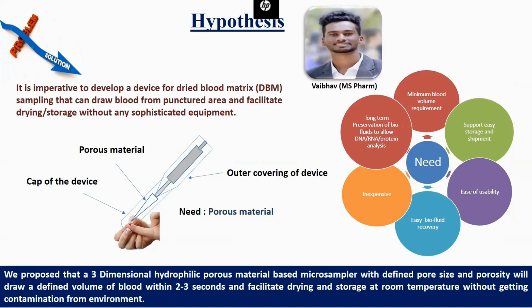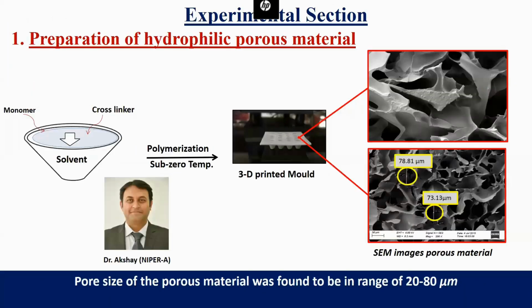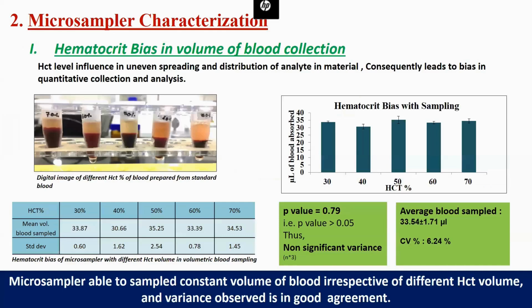So with the help of this MSc student who worked with me, we developed this device. How did we do it? We created a specialized hydrophilic polymer material with the aim of IP protection. I am not going to share the chemical name, but we had some hydrophilic polymer material that we tried to polymerize to form a microporous structure, which you can see in these images. And these microporous structures were tailored and tuned so that the microporosity is consistent.